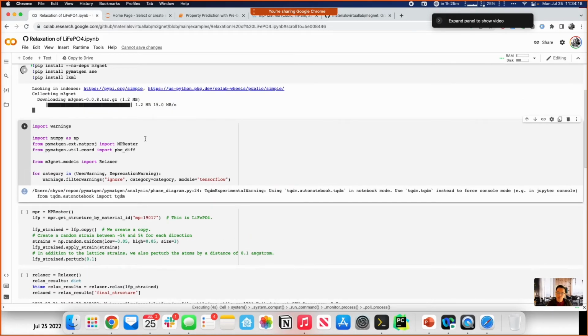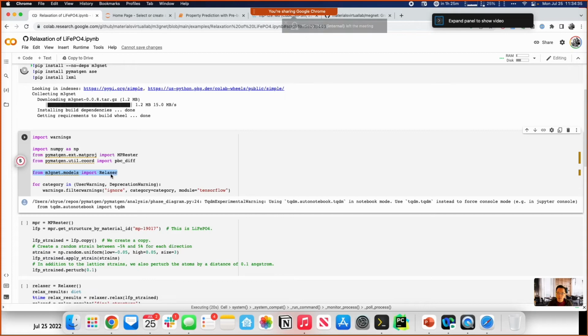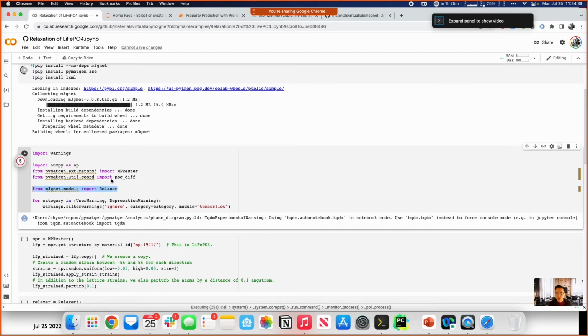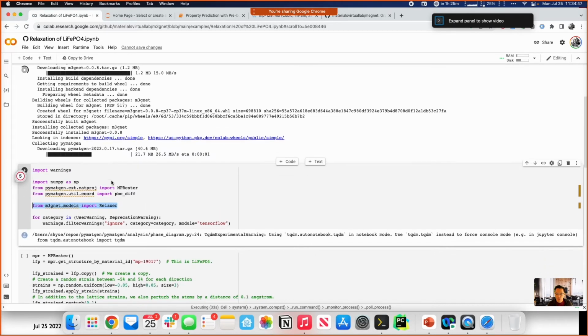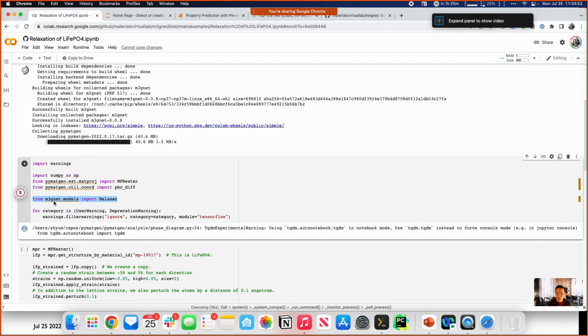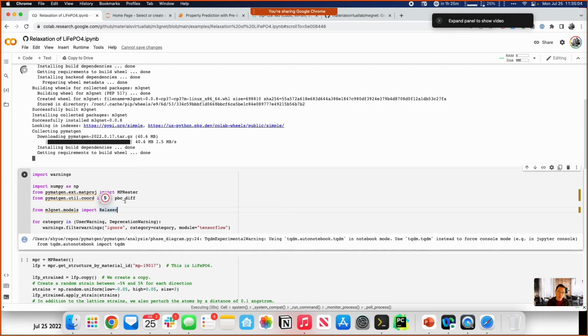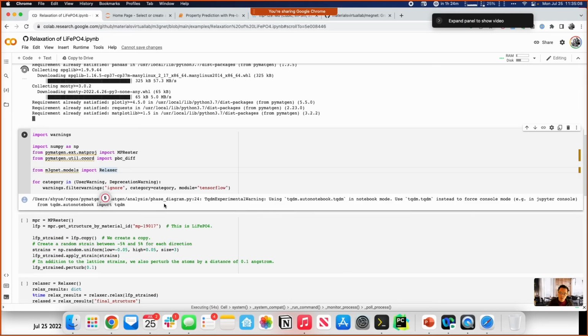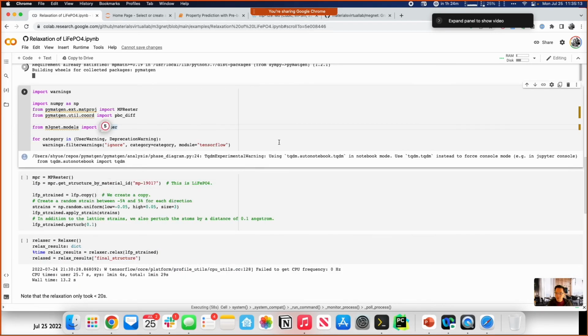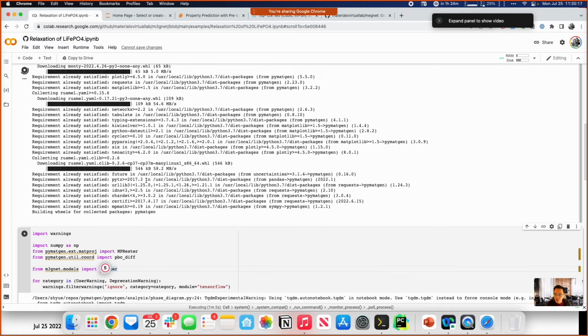Okay, so again, we are going to use MPRester to basically obtain our initial structure for lithium iron phosphate, which is a very well-known cathode material. And in the M3GNet repository and package, we have already pre-built our potential, the universal potential, and you can use it out of the box without any further training. Okay, so the one that we need to import is basically from m3gnet.models. You need the relaxer, which basically does crystal structure relaxations. What that does is that it uses the M3GNet potential together with ASE, which is the Atomic Simulation Environment package, to perform crystal structure relaxations. Okay, so I think that install is almost going to be done.